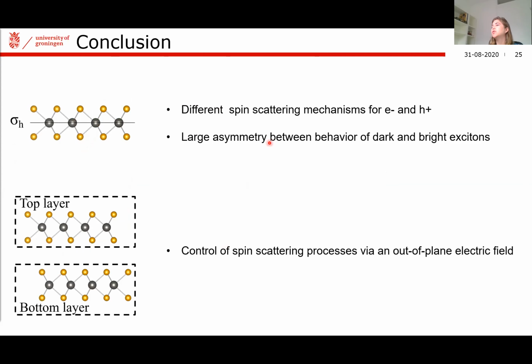So I hope I showed you that for monolayers, we can go through a very simple group theoretical approach to obtain the symmetries of the eigenstates, and those symmetries are very different for valence and conduction band states. So that will give different spin scattering mechanisms for electrons and holes. And this actually does lead to a large asymmetry between the behavior of dark and bright excitons, and that has been experimentally observed. Now for the bilayer, despite the presence of inversion symmetry,